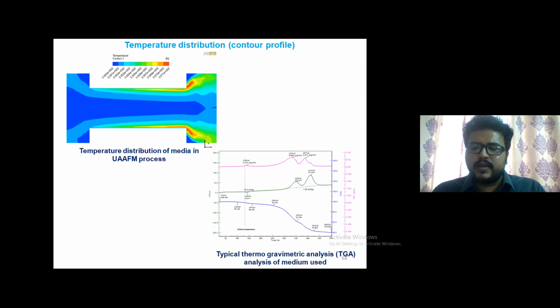So we have studied experimentally and also from a simulation perspective, and we concluded that by giving ultrasonic frequency externally to the workpiece, there is no effect on the temperature of the medium, right? Why I am telling this is we are using a semi-solid medium, and if the temperature increases, the stability of the abrasive particles will decrease, so they will settle down. So we also studied temperature distribution from the simulation point of view as well as the experimental point of view. In the experiments, you can see the TGA analysis has been done on the developed AFM medium, right?